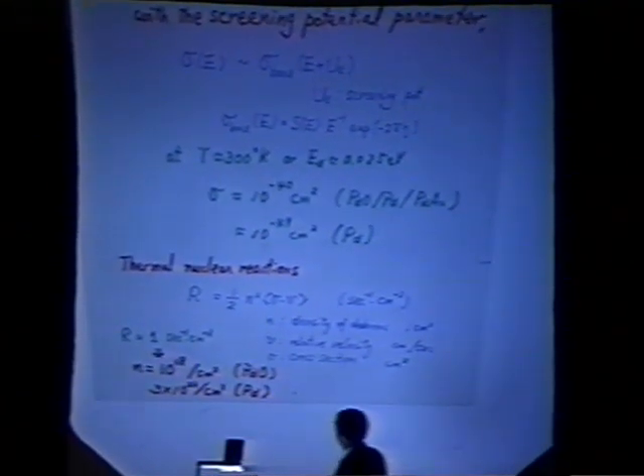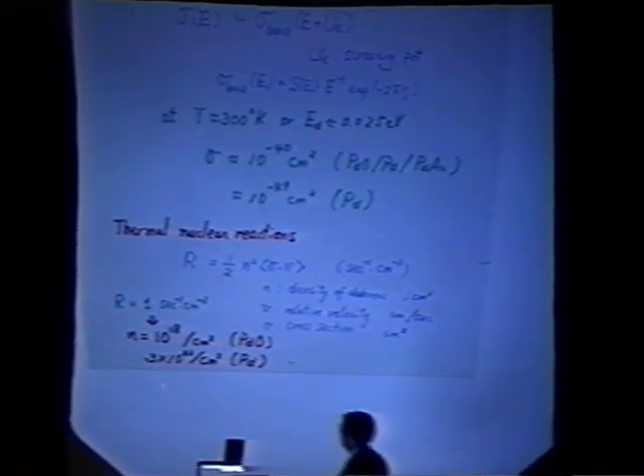Then at room temperature, or let's say a relative kinetic energy of a deuteron of around 0.025 electron volt, the cross-section is of the order of 10 to the minus 40 square centimeter. And for the palladium case, it is this one. And if we apply this to thermonuclear reactions, we get one nuclear reaction per cubic centimeter per second, if you have a deuteron density of 10 to the 18 per cubic centimeter for the palladium oxide case. So I have to stop here, but I just wanted one slide over there.